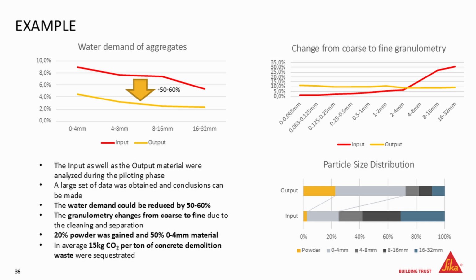What you can see is that for all the fractions, on average, we could reduce the water absorption by 50 to 60%, so very significantly. And when you look at the values, and that's the feedback we got from concrete producers and contractors, below 4% you can somehow handle, but more than 8%, or between 8 and 10%, that's far too much.